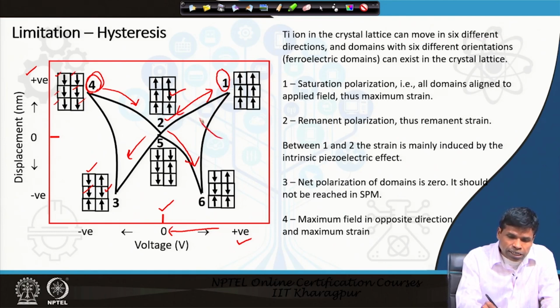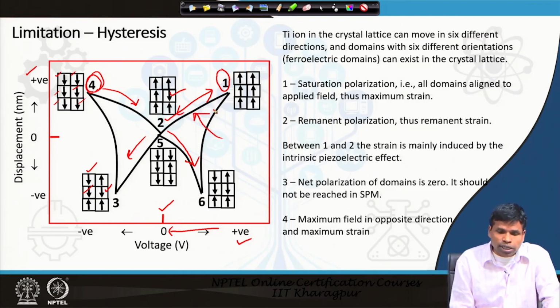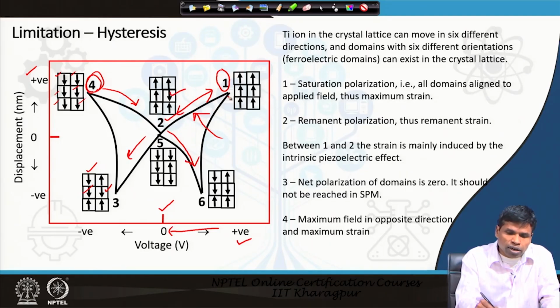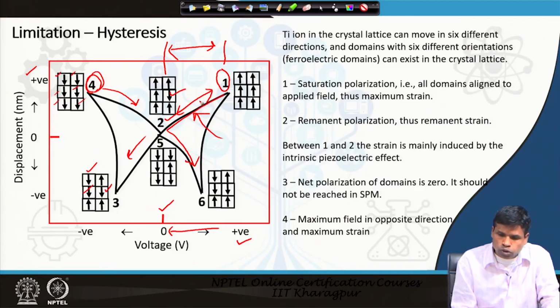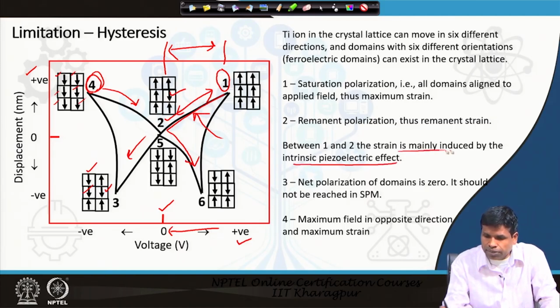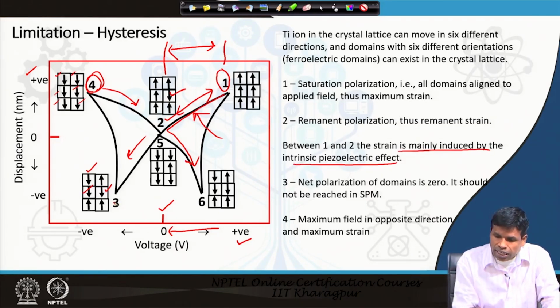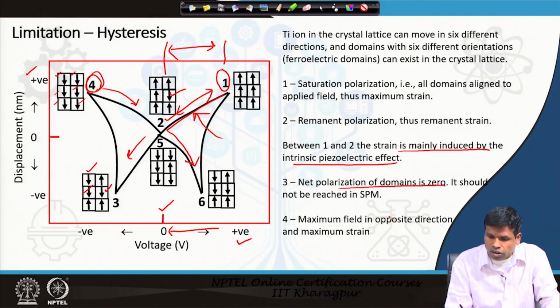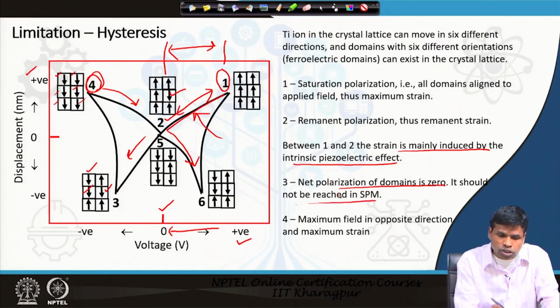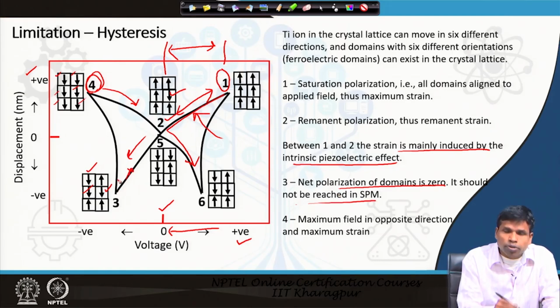the displacement in these cases is due to the intrinsic effect. Between 1 to 2, this is a unipolar operation, that is only in the positive direction, where the orientation changes from one to another, and the displacement change here is due to the intrinsic effect. Between 1 to 2, the strain is mainly induced by the intrinsic effect, and at 3, the net polarization of the domains is 0. So, in actual scanning probe microscopy, it should not reach 0, otherwise it will be complete depolarization, and at 4 there is maximum polarization.